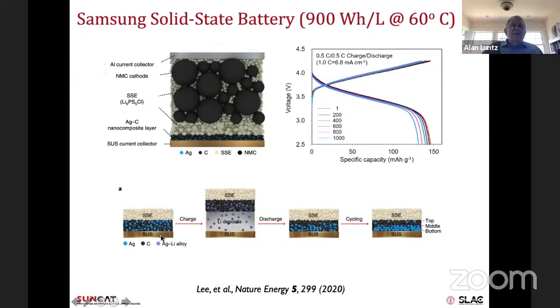And if you just focus on that, what actually happened was when they charged this material to plate out lithium, the silver carbon composite floated to the top. The lithium was all deposited below, and it made an alloy in here. And then when they went back, the silver went back into the carbon and so forth on down. It concentrated a little bit, but stayed. And with this, they were able to get a very practical discharge and charge for over 1,000 cycles. So this is the discharge of the battery, and it's stable to about 1,000 cycles. And then the charge of the battery. They lose a little bit of capacity, but not too much. Exactly how this worked is unclear. It was unclear to the authors, it's unclear to me, but it clearly has something to do with the alloying wanting to stabilize the lithium down below this material.